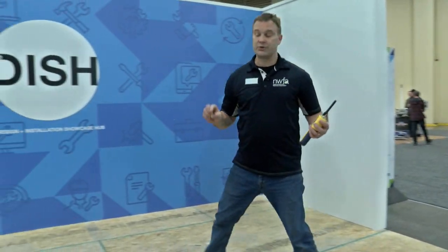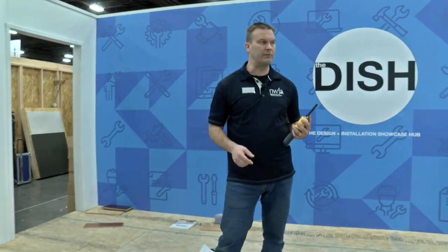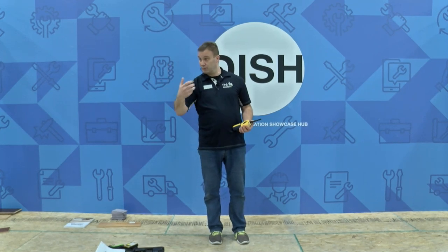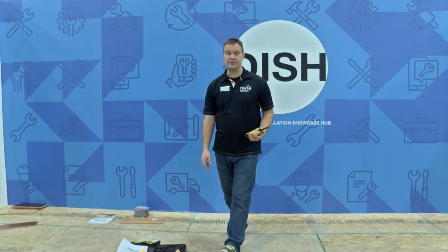If you're looking at concrete and want to know if it has the correct porosity, a good initial test is to drop water on it. If it beads up, there's a good chance it's either very slick or there's a sealer on top. We don't know if that sealer will be compatible with the adhesive. So quite often you'll have to do additional grinding to remove the sealer, rough up the surface, or use bead blasting or shot blasting to get a more porous surface to adhere to.